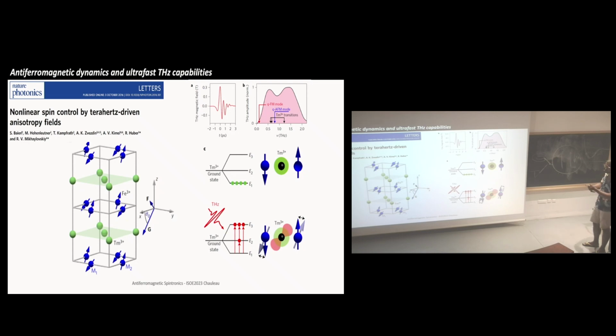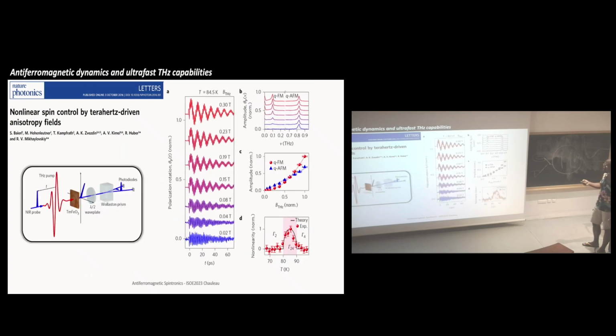And this kink in anisotropy will trigger the dynamics. And once again, I will not go through the detail of the paper because it's very, very rich, but what they do very nicely is that they can see the terahertz resonance of this material. So this really illustrates the fact that antiferromagnetic materials are kind of peculiar, and one of their main features lies in their terahertz capabilities.